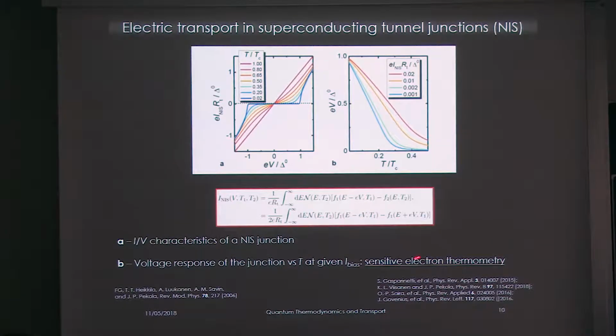So this is a very sensitive electrothermometry. If we want to classify this thermometer, I would say that it is not an absolute thermometer, because it relies on the superconducting energy gap in the density of states. But if we have calibrated it, it becomes a sort of primary thermometer. So what we do typically is to make a calibration in every experiment against the thermometer existing in the fridge. We go down in temperature, we calibrate this curve with the thermometer in the fridge, and then our thermometer becomes a sort of absolute thermometer that is in situ. It can be used in every structure, you can have as many thermometers as you wish, to measure different positions and different reservoirs. So this is the concept.